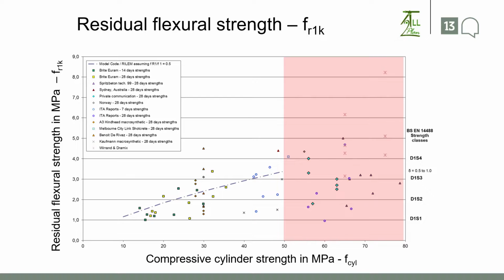And what I'm plotting is the strength of the concrete across the bottom versus, in this case, the first residual strength. So after the concrete is cracked and it drops down, that's the residual flexural tensile strength there. And if that, for example, was half of the peak, and the peak strength is basically driven by the concrete, the fibers don't affect that, it's the natural strength of the concrete typically, so if it drops to half, that would be the line that you see here typically.